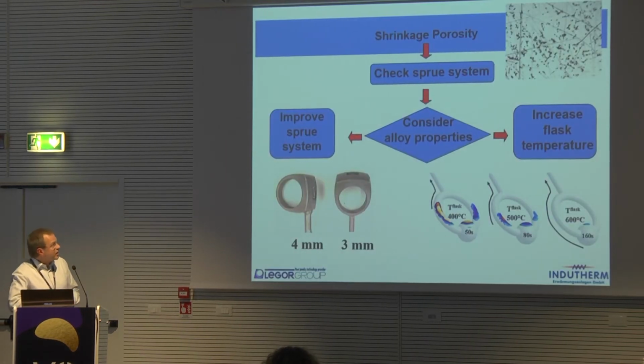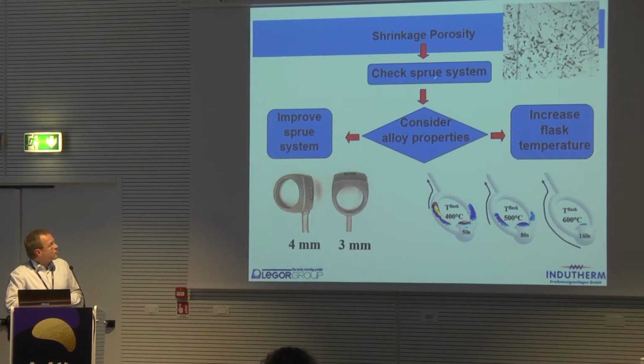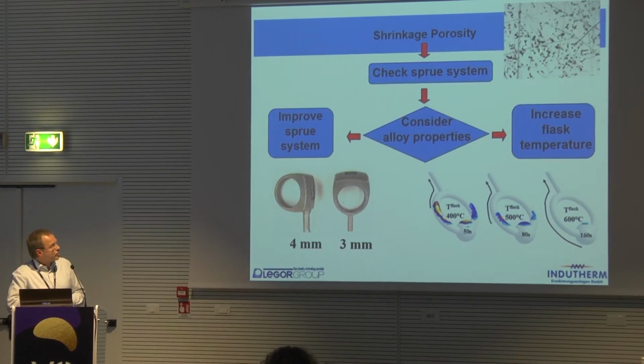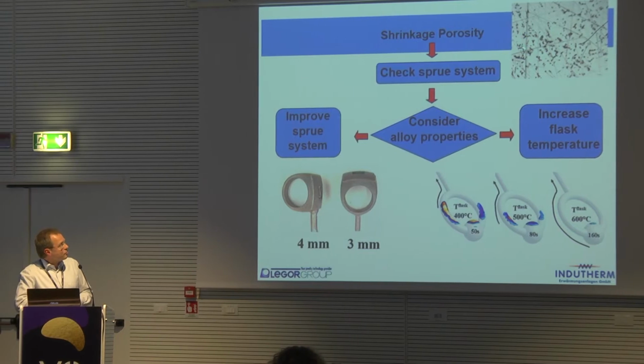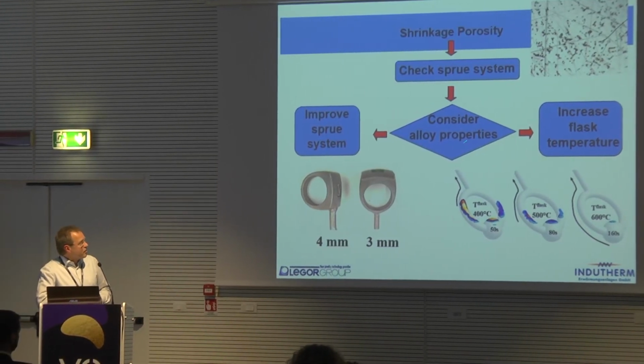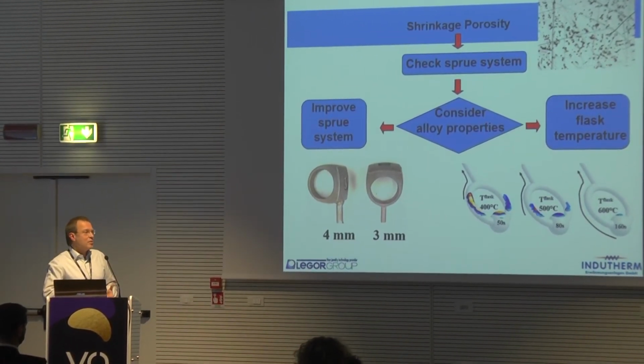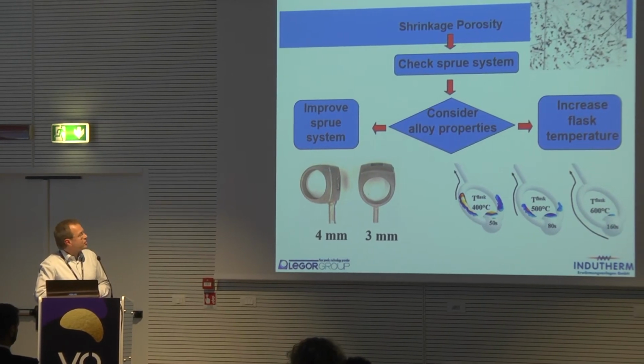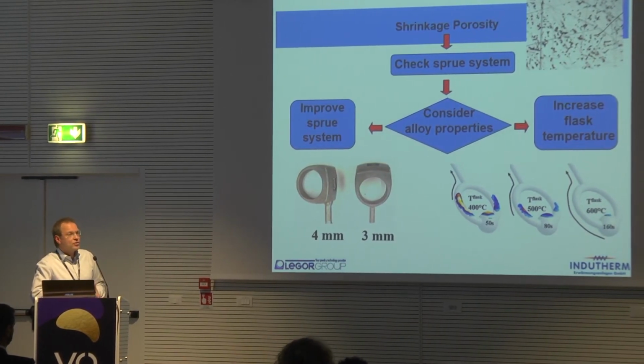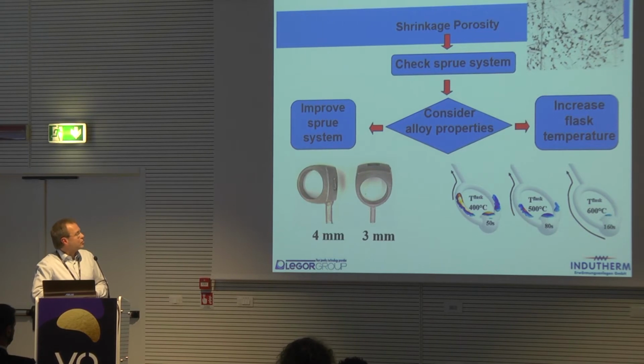So just a guideline, check the sprue system if you can identify shrinkage porosity on the polished surface. Think about the alloy properties. Some alloys are more prone to shrinkage porosities than others. Typically, sterling silver is less prone to shrinkage porosity than most gold alloys.